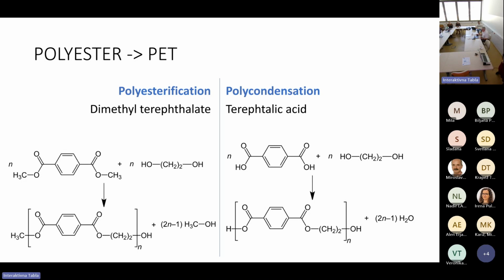In the first case, polyesterification, ethylene glycol and dimethyl terephthalate are used as monomers, and methanol is produced as a side product. And of course, this side product has to be removed during polymerization. The other way of synthesizing polyethylene terephthalate is polycondensation using terephthalic acid and ethylene glycol. In this case, water is produced as a side product. And of course, if you want to obtain high molecular masses, water also has to be removed. It means that these reactions are performed under vacuum.